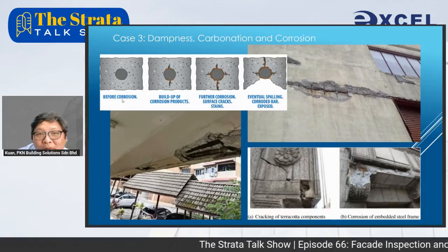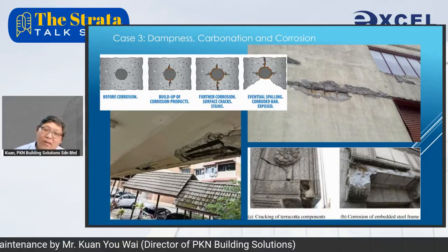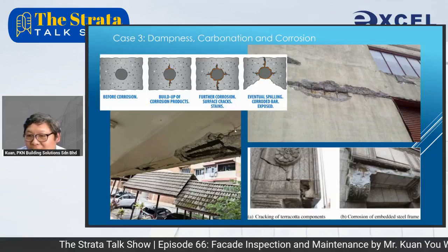Cracked concrete has no compression strength. Corroded reinforcement steel bar is compromised in tensile strength. As a result, the structural performance dropped significantly, subject to the level of intensity of corrosion. And this is very common again in Malaysia due to our hot weather, which accelerates the corrosion, humid environment, you know, strong precipitation that gives a lot of conducive environment or factors that cause the corrosion to trigger.